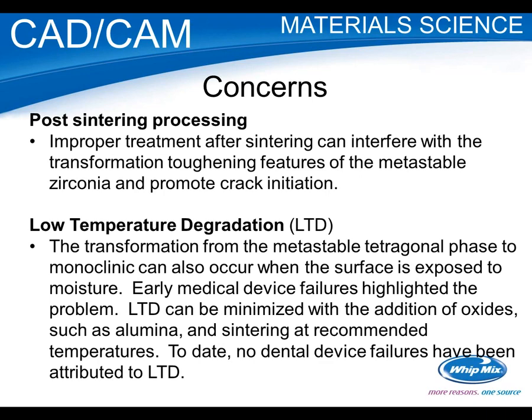If you talk to some of the experts, especially the experts that went through a terrible time with failures in patients, they are very sensitive to this issue. And when we look at the higher translucent brands of zirconia for dental, what they've done is they've reduced the amount of alumina. And so your experts are kind of concerned with that. But other experts point out that there haven't really been any device failures.